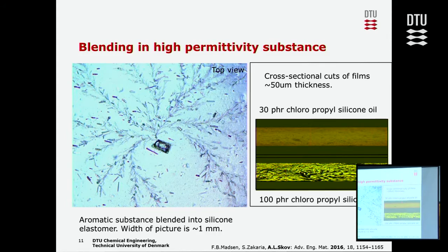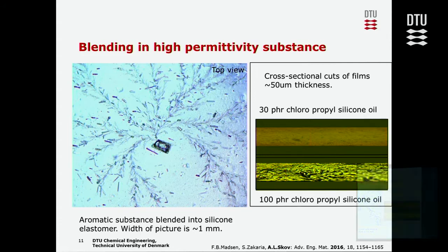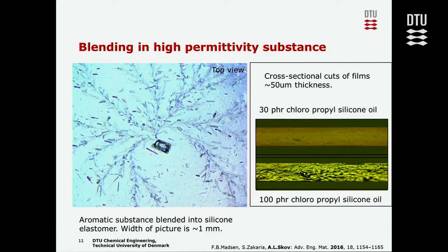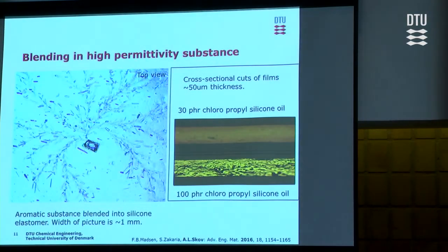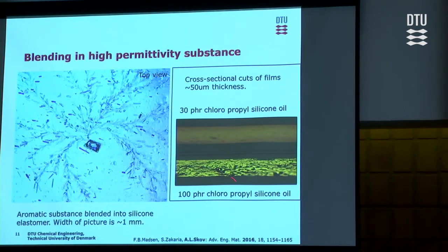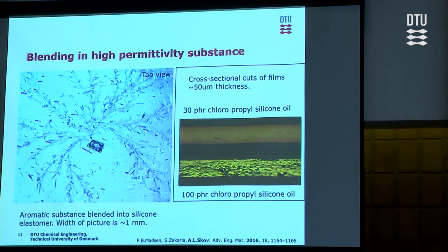But on the other hand, we then tried to work with some more miscible polymers. So we have a chloropropyl silicone oil with a few of the methyl groups replaced by chloropropyl groups. And here we have 30 phr of the chloropropyl oil in our silicone elastomer matrix. phr is parts per 100 rubber. And here we could get nice homogeneous properties. But when we have 100 phr, so that is 50% by volume of the oil, we actually still had a very nice elastomer, but we could see from a microscope image, which is actually the width of the film we have here, that we had very much phase separation on the local scale.